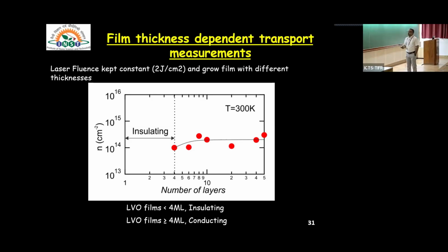To check this, we took 2 joule per centimeter square, which is above the critical energy of this laser fluence, and we started growing different numbers of monolayers of lanthanum vanadate on top of strontium titanate. What we have seen is that even above the critical laser fluence, below 4 monolayers this system remains insulating. Above this critical thickness it becomes conducting, and this is approximately 3 times 10 to the power 14, which is kind of half an electron doping per unit cell.